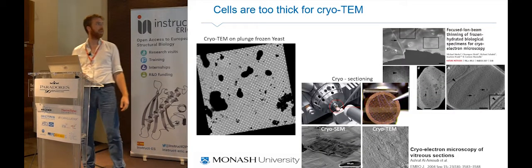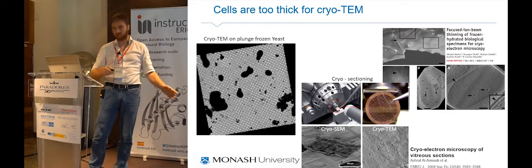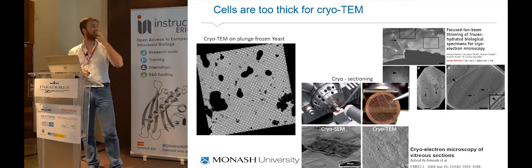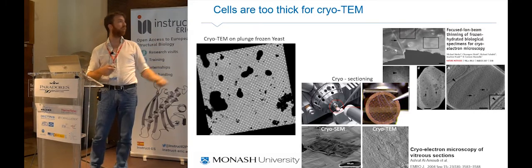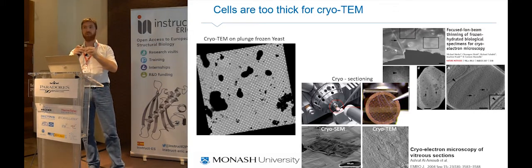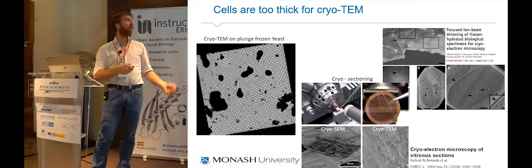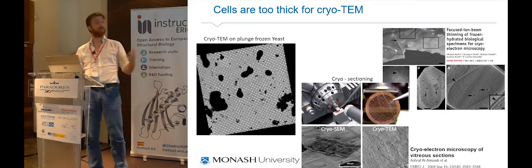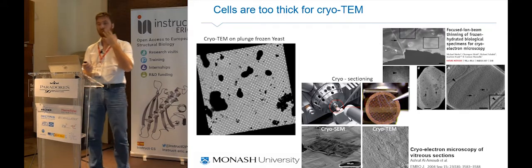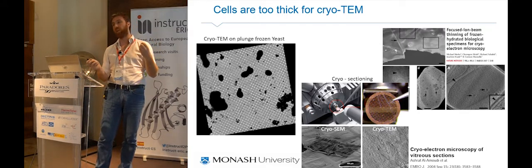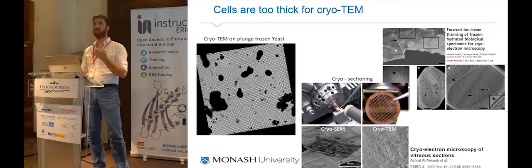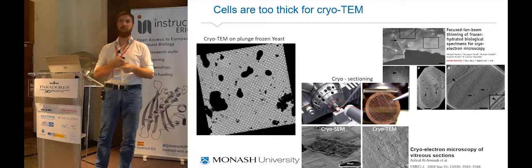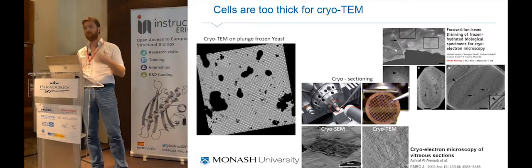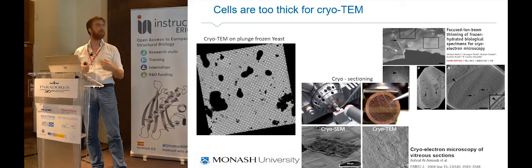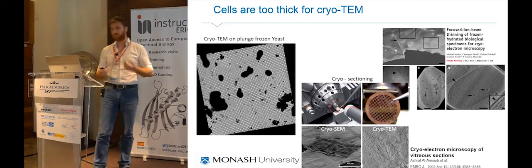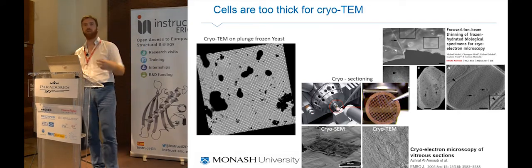One is cryosectioning. It's a beautiful technique, but nobody really wants to do that because it's very hard to get samples of good quality, and your thickness in the section is limited to 50 to 70 nanometers. So nowadays, basically, everybody's doing focused ion beam. What we know in terms of focused ion beam milling is that the throughput is not quite high. You're making 10 lamellas, 20 lamellas a day in some cases, but it's very low.